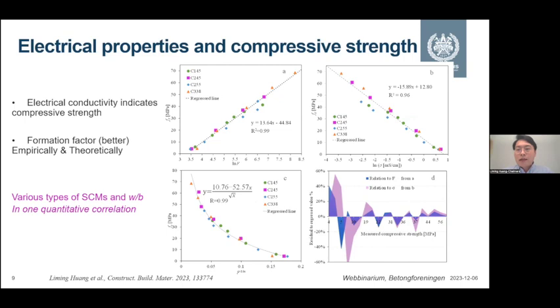But in general, we try to describe and validate this identified correlation between formation factor and the compressive strength. Firstly, we have a look at figure B, which describes the correlation between electrical conductivity and the compressive strength. In general, it describes a good correlation, but if we transfer the electrical conductivity of paste into formation factor by using the conductivity of pore solution, we can get a better correlation between the formation factor and the compressive strength. In both A and C, we can see it describes very well. This means that this parameter can indicate the strength development of concrete with different types of SCMs and even different water to binder ratios in one equation.